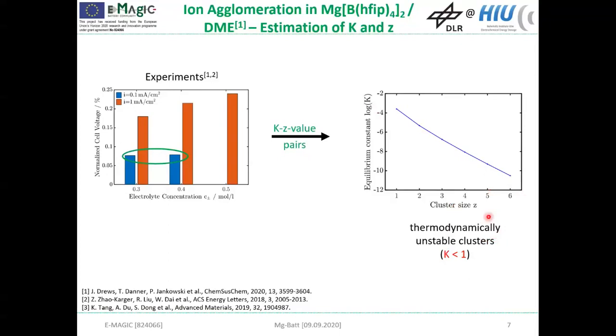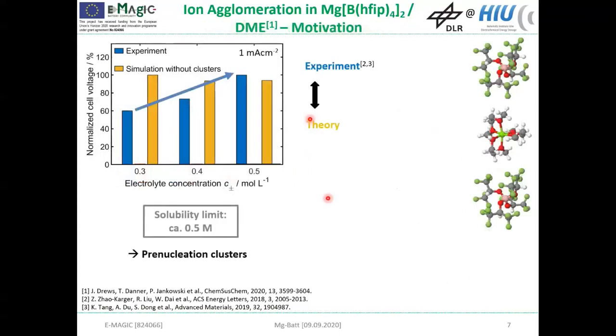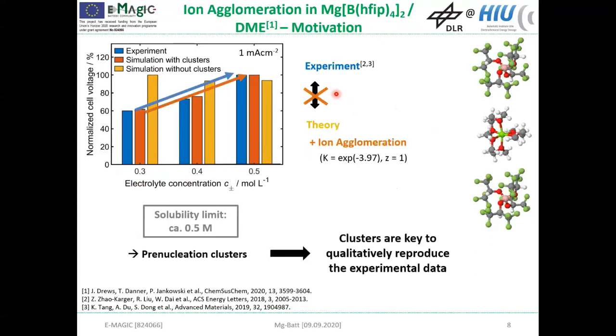So now that we know value pairs for K and Z, we can come back to this comparison between the experiment and the theory. Without considering any clusters in our model, we weren't able to reproduce the experimentally observed concentration dependence. But when we now include the ion agglomeration and use the determined K and Z values, we can qualitatively reproduce this experimental data. So consequently, the clusters are key to explain the measurements from our partner.